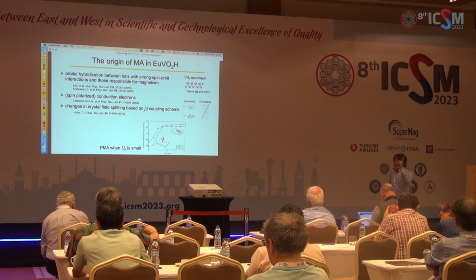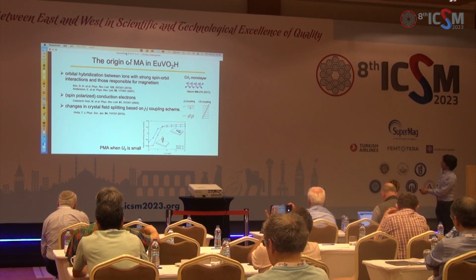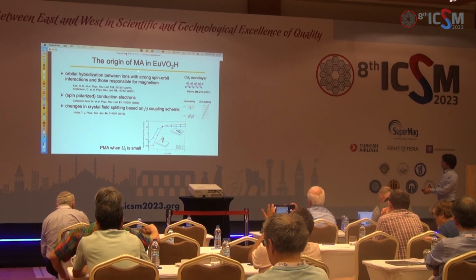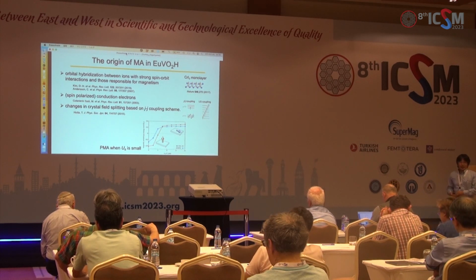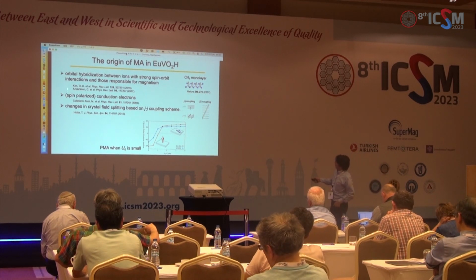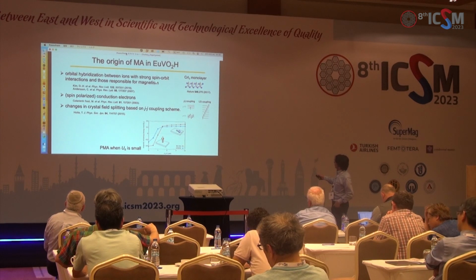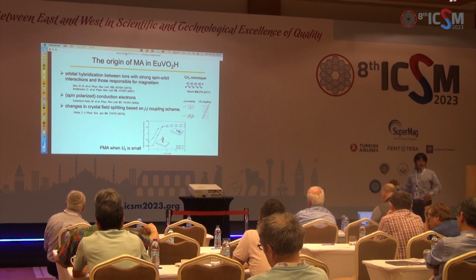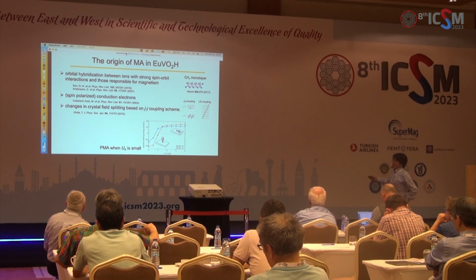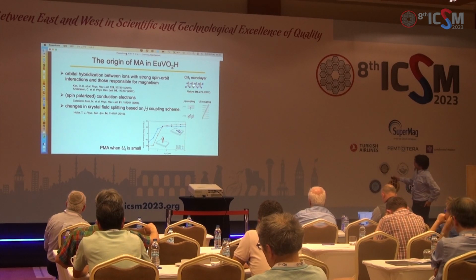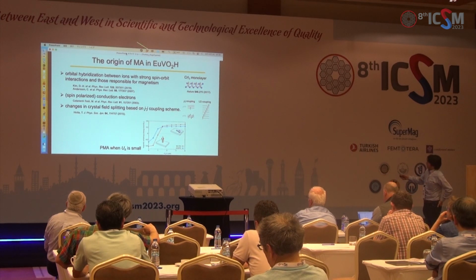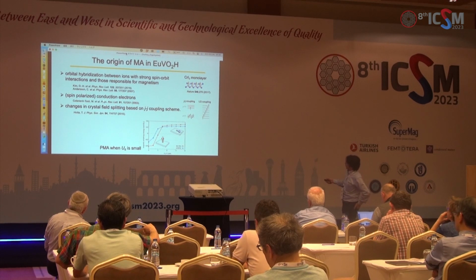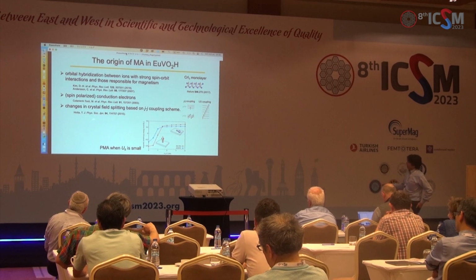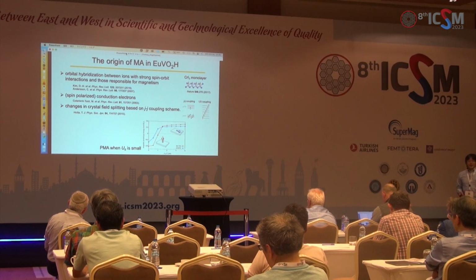So, in terms of the perpendicular magnetic anisotropy, or larger magnetic anisotropy, we may consider several scenarios, which is not clear, but we consider these possibilities. One is the orbital hybridization between ions with strong spin-orbit interactions and those responsible for magnetism. Actually, in this symposium, some presentations about magnetic anisotropy are shown. And for example, in the chromium iodide monolayer case, because the iodine ion is very heavy, such spin-orbit interactions should be considered. Another scenario includes spin-polarized conduction electrons, as shown in this paper, or changes in crystal field splitting based on the jj coupling scheme.